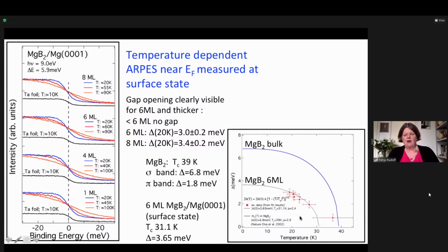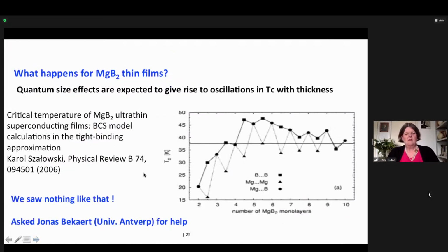We can also follow how this changes with temperature. We did these measurements because there had been these predictions. The prediction had been that the critical temperature should go like this. And that was not at all what we were seeing. We were very surprised, and these oscillations were supposed to come from quantum effects, etc. And we didn't see anything like that.